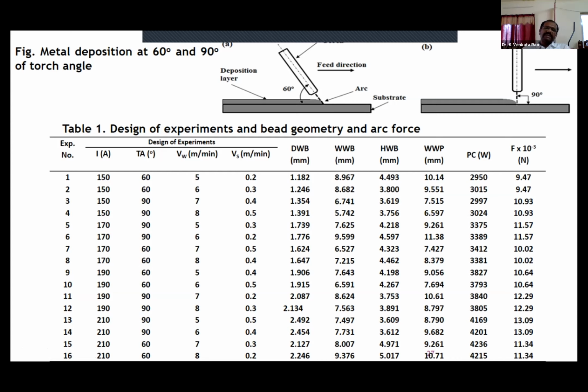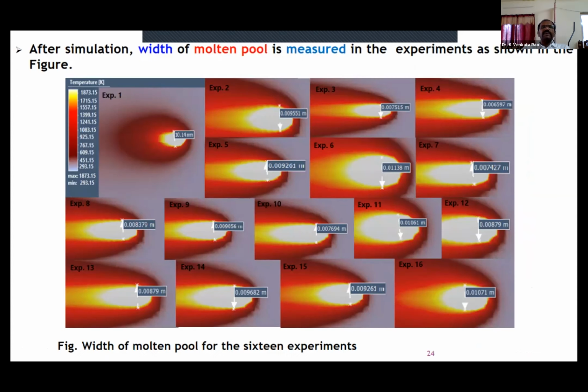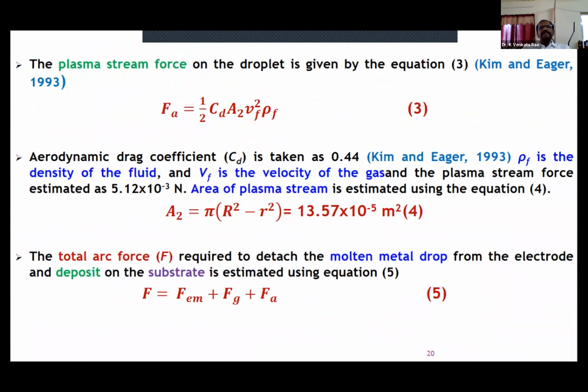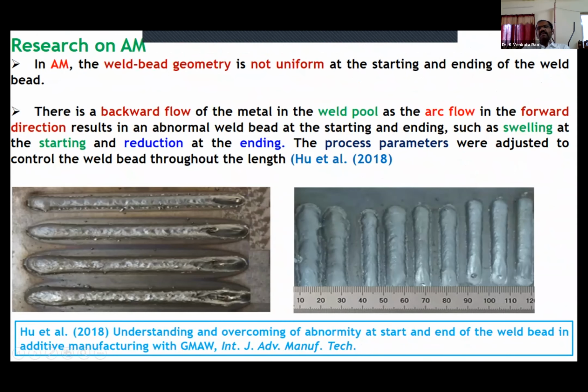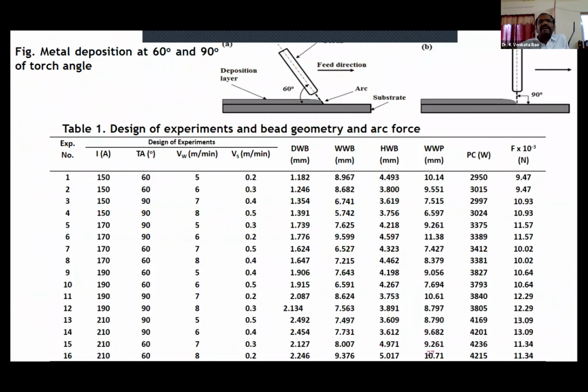See this one, the weld beads formed on the plate. We cut this plate across this one. Generally we followed the wire EDM. Using that wire EDM technique, we cut that one. Under the microscope, we measured the width of weld bead. See this one, depth of weld bead, width of weld bead, height of weld bead.